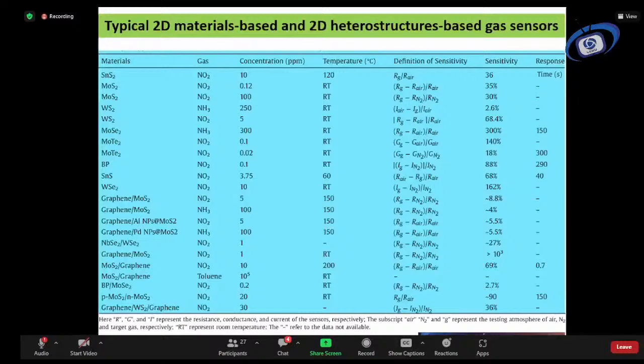For the heterostructure, if we want to develop a heterostructure among those materials, I have put one table here to show which kind of material can be used for what kind of gases, and their selectivity, sensitivity, response, and how much concentration we can detect at what temperature. So you can see, for example, SnS, MoS2, WS2, MoSe2, and MoTe2. All these materials show maximum response at room temperature, in the third and fourth columns.